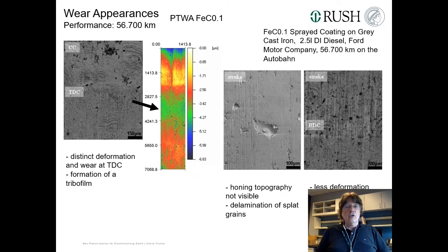To cut a long story short, we checked the surface in the stroke, which is very well lubricated. So from reaction products from the combustion chamber, which are introduced, you get some scratches here. Sometimes a splat grain falls out, but nobody really cared about it because this gives you an additional oil retaining volume. The bottom dead center looked not quite the same because there we found remains of a strain gradient, but more or less these both areas were not really a problem.